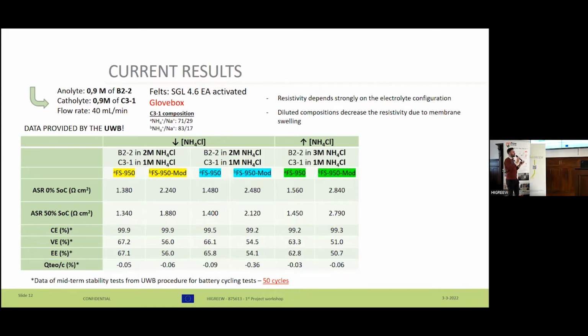So the membrane behavior will be different. The data collected in this table was considering this electrolyte configuration as the other slide, which was 900 millimolar of the active species and ammonium chloride, but different concentrations of the supporting electrolyte, which is the ions that are supposed to exchange in our membrane. And in this case, cationic, so the ammonium ions.